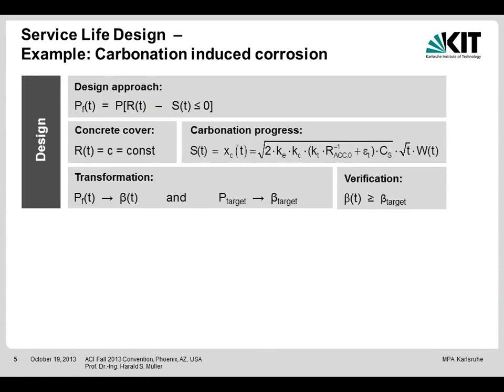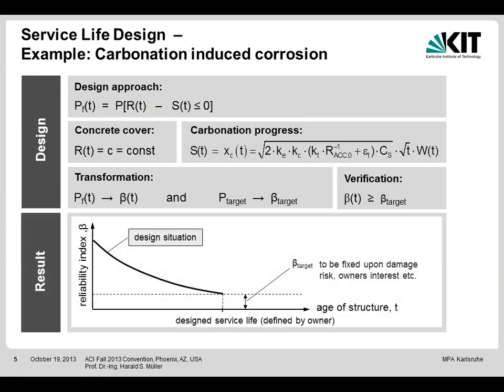How this method works. If we look at the very simple example, carbonation-induced corrosion, then that is the basic formula for the design approach. You have your resistance, the concrete cover, and the carbonation process. And important, normally we do not talk about failure probability, we talk about reliability. It sounds much better. It is from a mathematical point of view the same, but it's better to speak of reliability than of failure probability. And if we look at the result, then we get the reliability index calculated from this formula over the age of the structure. This is a design situation where the owner, for example, defined the service life of his structure, and this target beta may be defined upon the damage which I am ready to accept, or the risk, or the owner's interest, or something else. You are free to do it in your calculation.